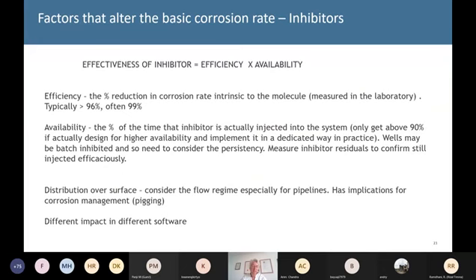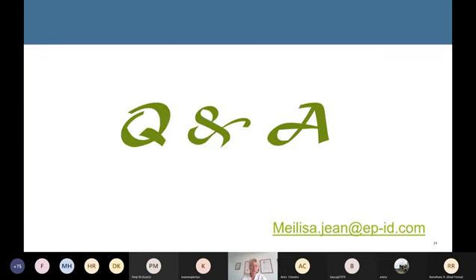Finally, inhibitors, fairly well established that the effectiveness of an inhibitor is the efficiency, which is normally extremely good because that's just on good chemistry. Get the right molecule and you've got a high efficiency. The availability is the inhibitor actually at the surface of your steel, and that depends upon the engineering system you've put in place, whether you're batching, whether you've got a good distribution of the inhibitor, and you need to measure the residuals to confirm that you've got a good covering of the surface by the inhibitor. We talked about flow regime, and different software systems use different approaches.